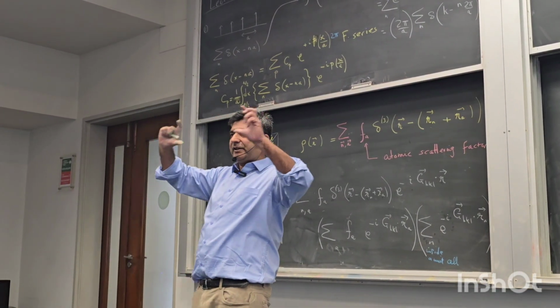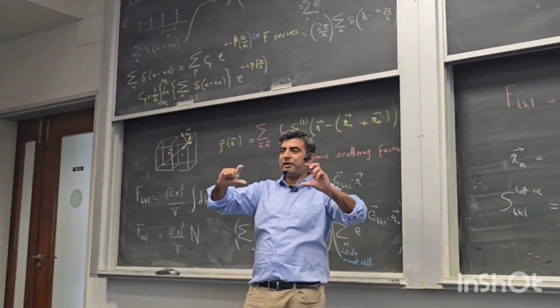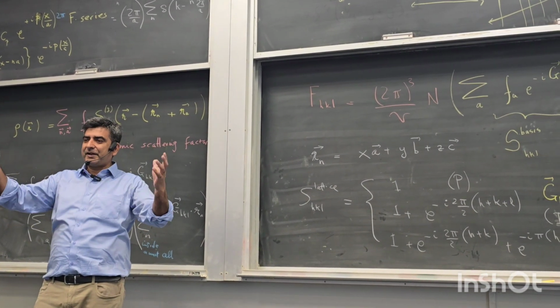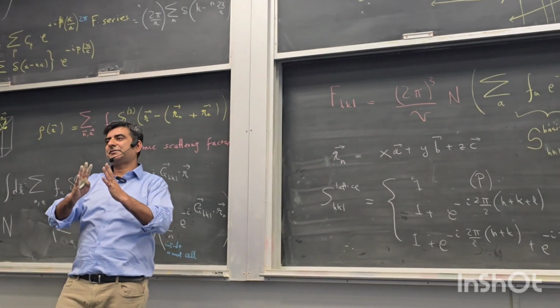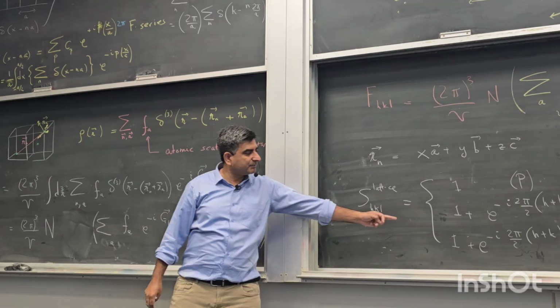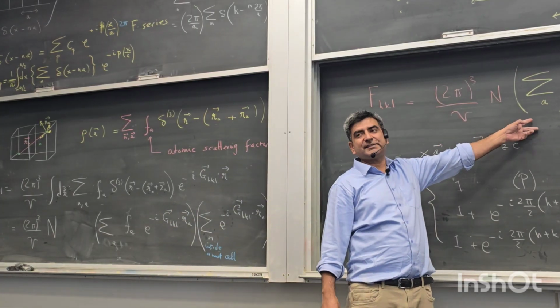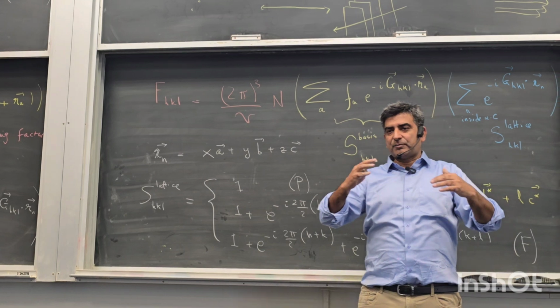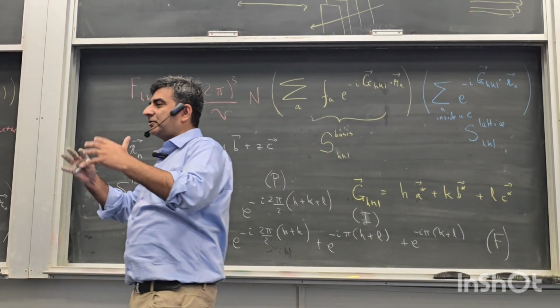That's what we've seen in our previous lectures as well, that for a body centered direct lattice, the diffraction peaks only exist when H plus K plus L is even. And this comes out from the structure factor. No matter what the basis structure factor is, the lattice puts certain constraints on the reflection.